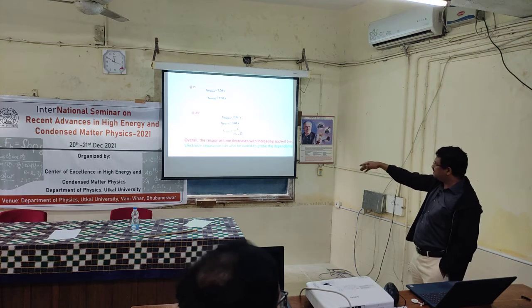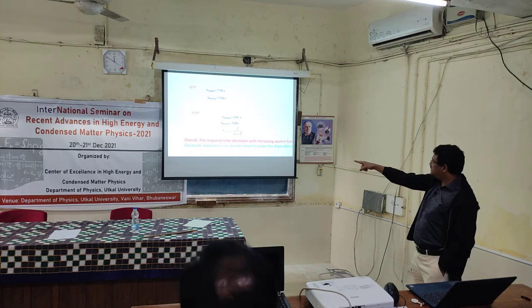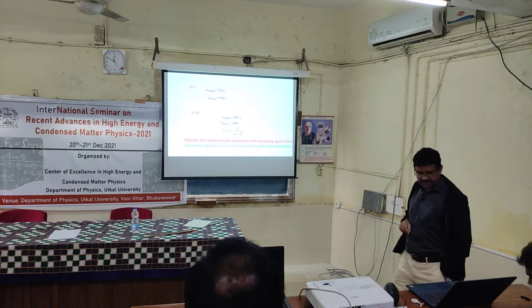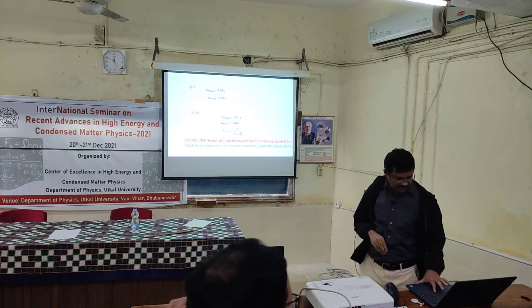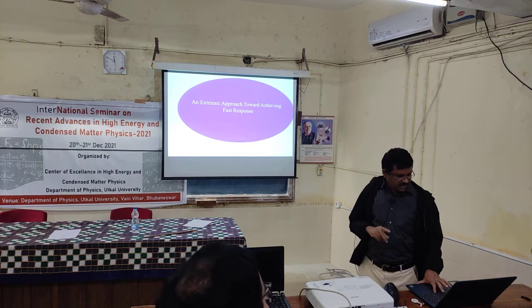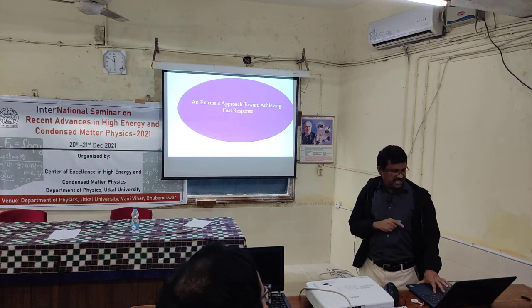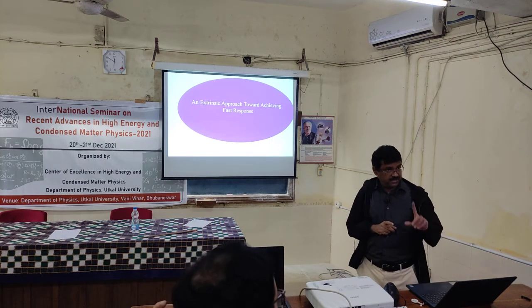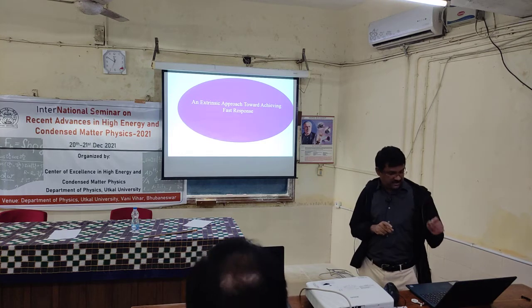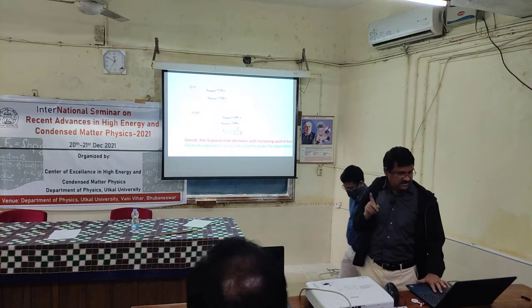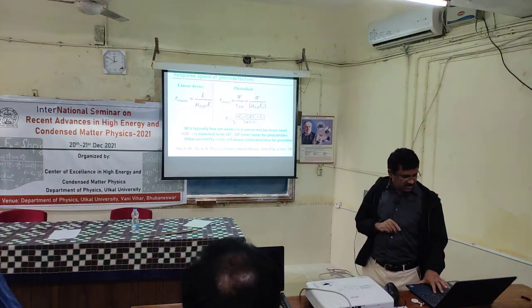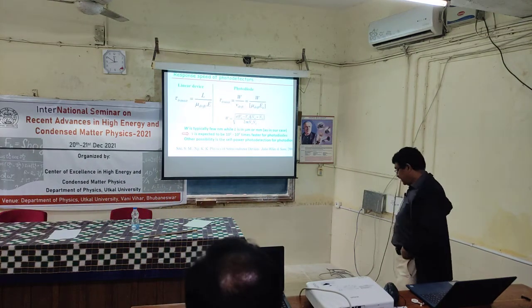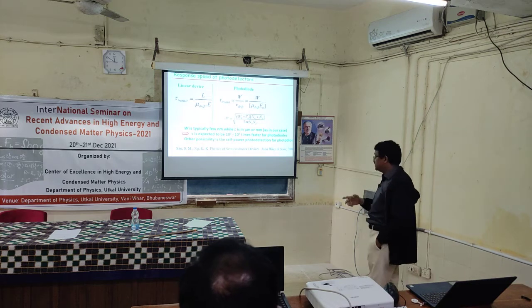And one can also do other studies, like electrode separation, especially for this device, to prove the dependency on the length of the electrode separation. Then we switch to an extrinsic approach for achieving fast response. In that case, you see this is in seconds, 7.76 and 7.52. So we thought about how we can make the response faster.